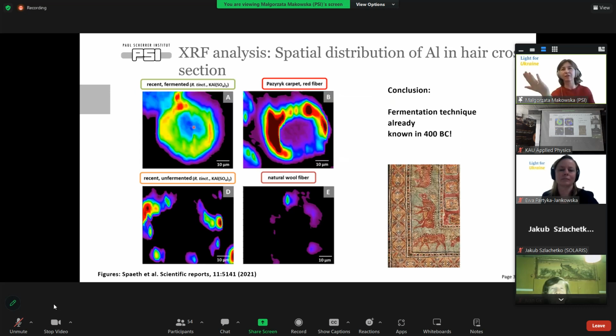So the point was that they did this mapping of aluminum in the fermented fibers, also fibers extracted from this carpet. And they noticed that they have aluminum also inside the fiber, while in the natural, unrefined fibers, the aluminum is only outside. Therefore, they concluded that this technique was known already 2,000 years earlier than people believed.